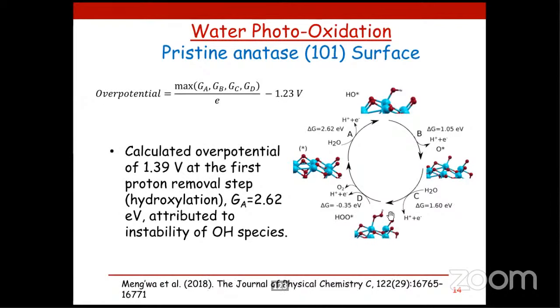Now, if you do this particular calculation, and remember that this is the photooxidation cycle, you can know that the highest Gibbs free energy, for the pristine anatase 101 surface, is 2.62 electron volts, and you subtract 1.23, you get that the overpotential is actually 1.39 volts. Now let's see what happens when you have the coupled oxides, like Cu2O over TiO2. The overpotential is actually reduced from 1.39 to 0.77 and 0.48, and this is a significant reduction compared to the 1.39 that you get in the pristine TiO2.